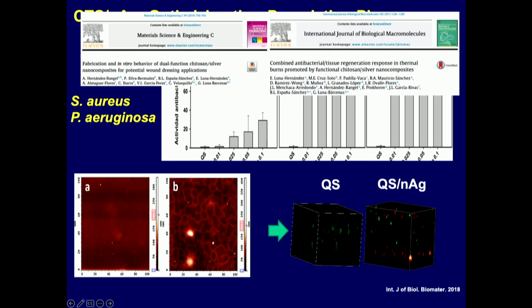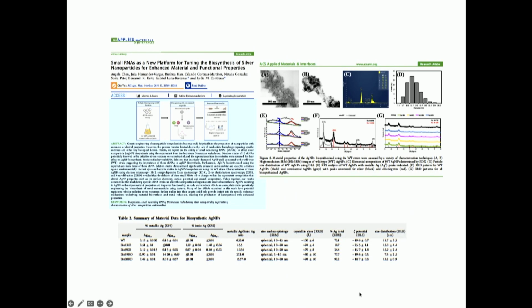This is confocal microscopy of proper design of materials with silver nanoparticles. Just to give you a feel of the things that we do, we have extended this treatment to address other aspects. In these recent publications, we have used a thermophile bacteria called Deinococcus radiodurans. In collaboration with my colleague Lydia Contreras at UT Austin, we were able to isolate the correct strands that are doing the reducing effect on the silver nanoparticles, to use for photodegradation of rhodamine and all that.